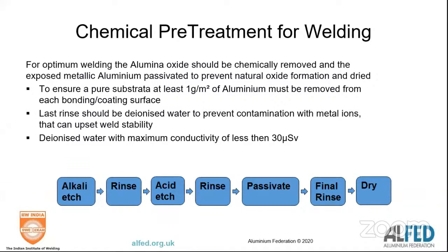What you need to be aware of is that your final rinse has to be deionized water. If your final rinse is not deionized water, in essence, what will happen is as you've passivated the surface, you've got a chemically active surface. What you're going to do is deposit all the ions, all the trace elements, back onto the surface and liberally coat the aluminium. In service, when they get wet, you're going to get corrosion. So whatever happens, your final rinse must be deionized water when you're chemically pre-treating.